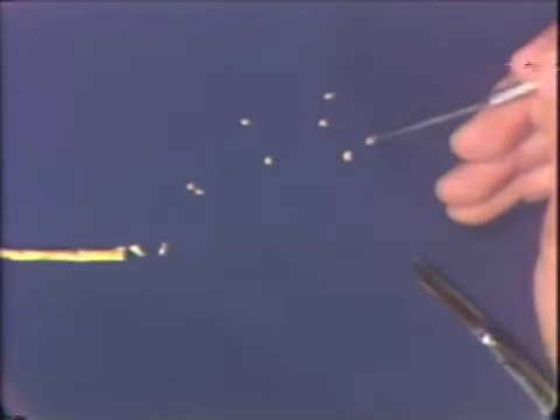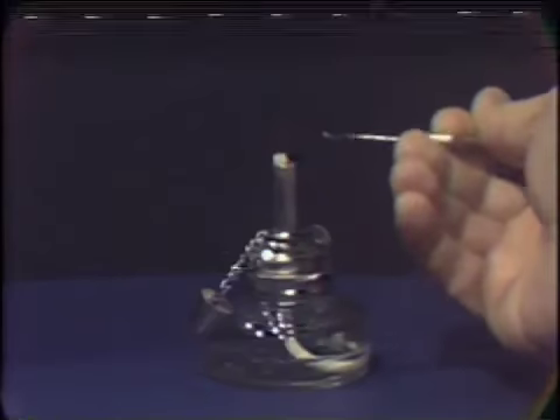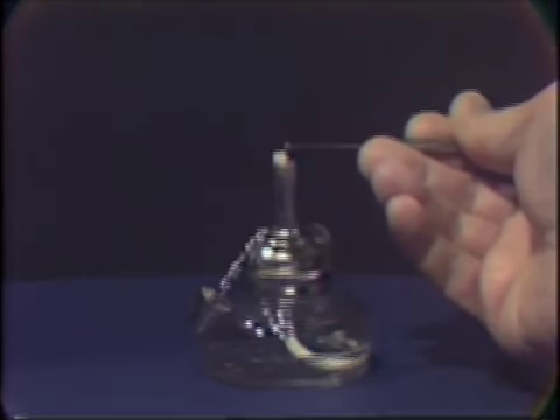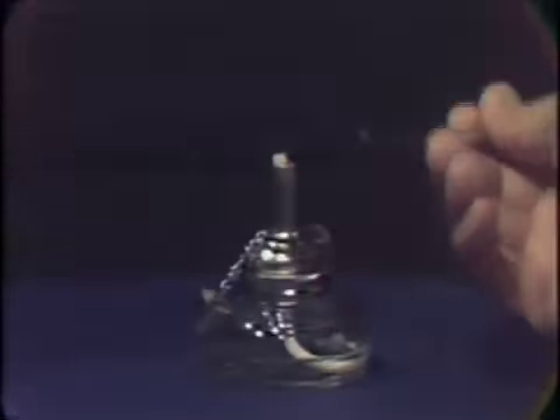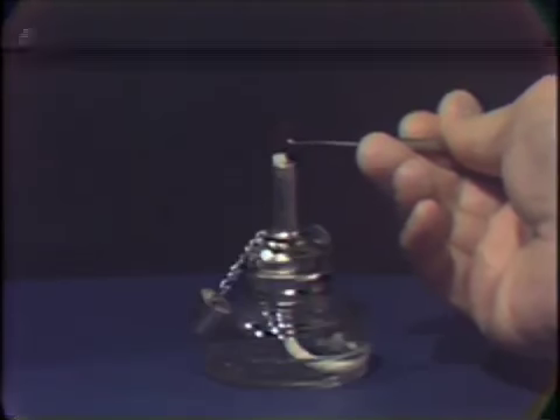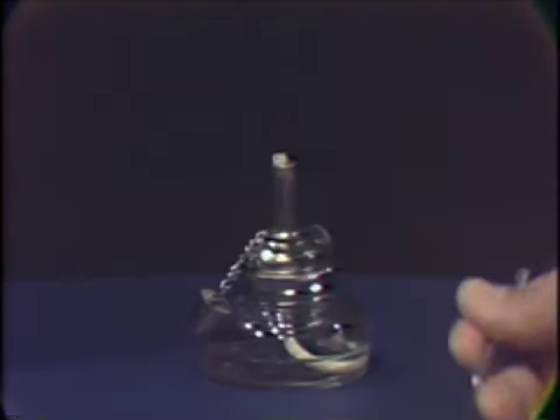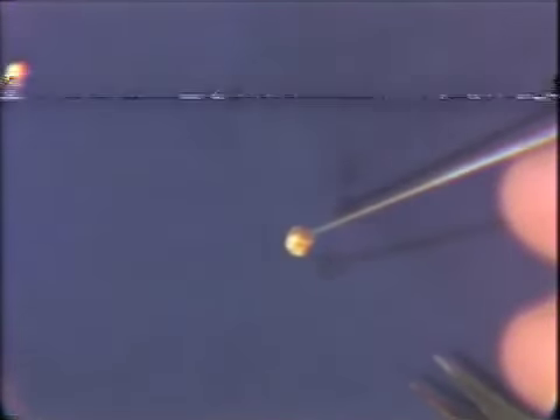Now we have a little larger pellet, a number 64 pellet. You see, if we try to attach these together, there is a lack of coherence at this time. If we would take these into the alcohol flame and anneal, let's set this one down to the side and now anneal another to bring about the coherence of the material. See, now as we touch these together, there is that physical characteristic of coherence that is developed.